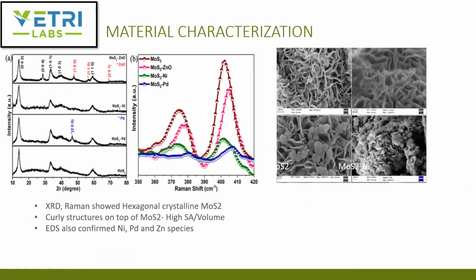Okay, material characterization. They further took the material and did XRD and Raman. If you look to the left, they showed the moly sulfide at the bottom of the XRD chart here. You can see a 002 peak, which shows the crystalline, hexagonal crystalline moly sulfide. Then as you grow palladium on top, you can have a typical signature 200. As you go to nickel, there's really no clear signature. Zinc oxide has a very clear signature.